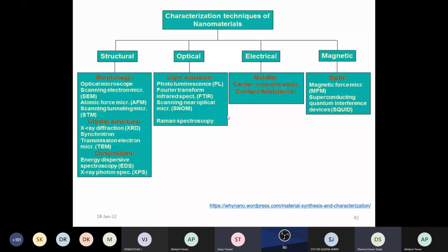But immediately after synthesis of your nanomaterial, UV visible absorption spectroscopy is the first step to characterize your nanomaterial. Because SEM and TEM are costly equipment, using UV visible absorption spectroscopy, you can get an absorption peak in a particular range. Suppose you have synthesized 50 nanometer gold nanoparticle, immediately take the UV visible absorption spectroscopy. Then if gold nanoparticle is there, around 550 nanometer, you will get an absorption peak in UV visible. Now you can go to electron microscopy, then you will find that similar spherical types of nanomaterial are formed.